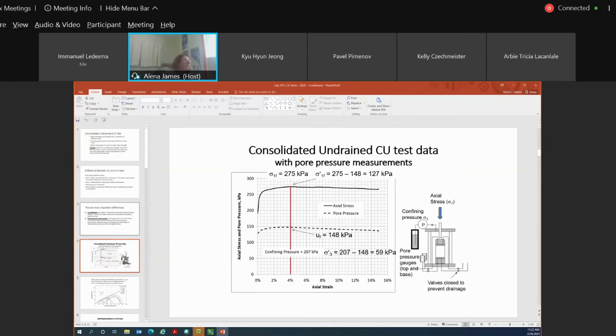Your pore water pressure at failure corresponds to the pore water pressure for your axial stress at failure. So you'll see that this data point right here represents your axial stress at failure. So if that represents your axial stress at failure, your pore water pressure at failure is determined by drawing this vertical line down to this point right here, and this data point represents your pore water pressure at failure. So that's a very important point to note with the CU test, that your pore water pressure at failure may not be your maximum pore water pressure value that's recorded.